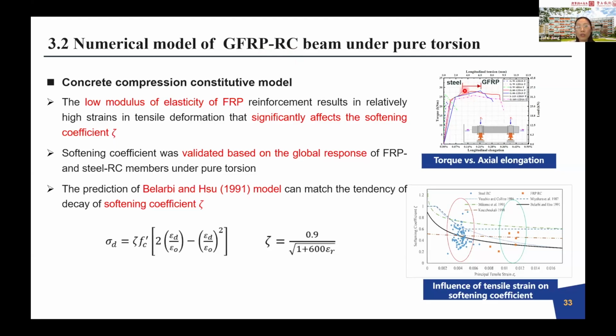As we showed here, this is a comparison between steel and GFRP based on the same reinforcement ratio. We find that GFRP has more longitudinal extension. We can also see in this figure that the compression behavior of the strut will be affected by the longitudinal straining. In this scatter figure, the steel is shown, and the orange is for FRP. So the elongation in FRP is much higher than in steel. So we find that several published or proposed softening coefficients do not fit FRP RC beams. Based on the current data, the coefficient proposed by Belarbi and Hsu is more suitable for FRP RC beams.